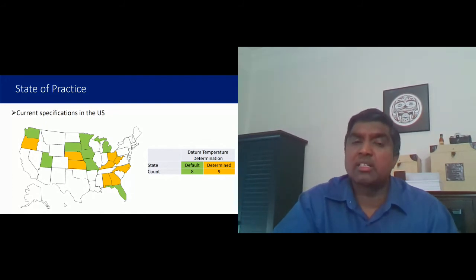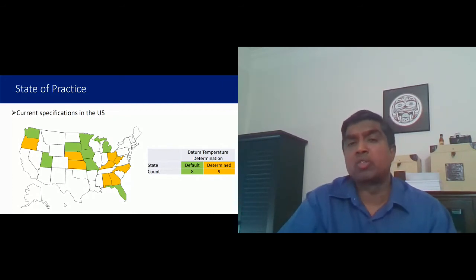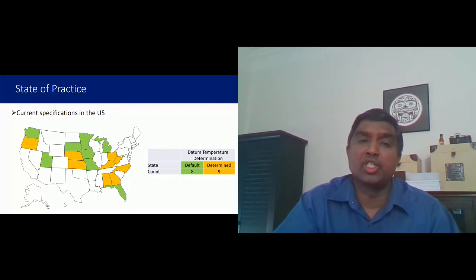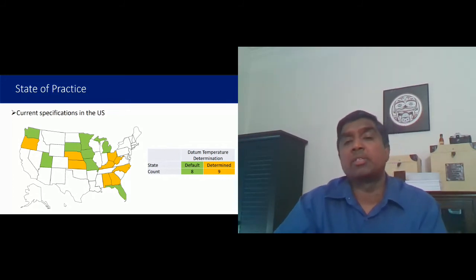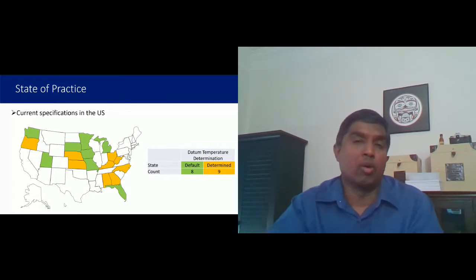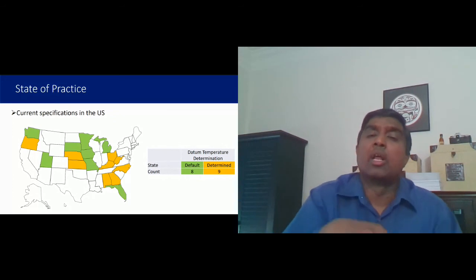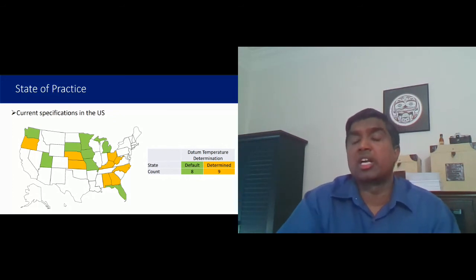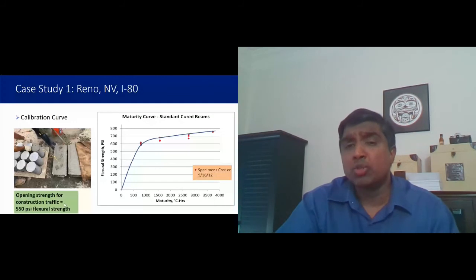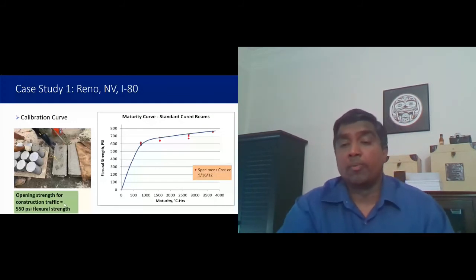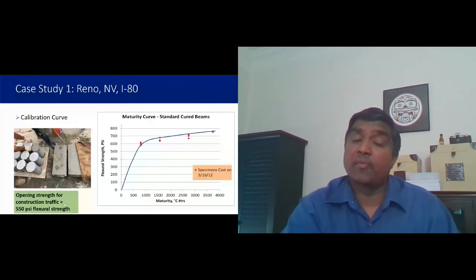If I'm not mistaken, the opening strength for construction traffic is 550 PSI flexural strength. So what we did was we made a bunch of beams and instrumented one of the beams with the maturity sensor. Then we broke the beams at different intervals of time, 1 day, 2 days, I think 3 days and 5 days, and we also measured the corresponding maturity number. Using that data, we plotted our calibration curve. So we know that 550 PSI is a flexural strength.